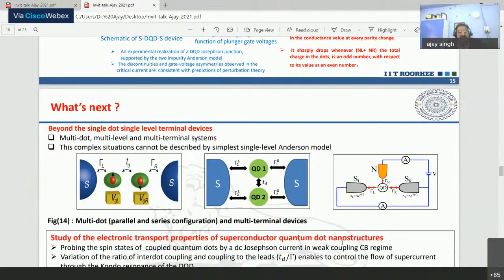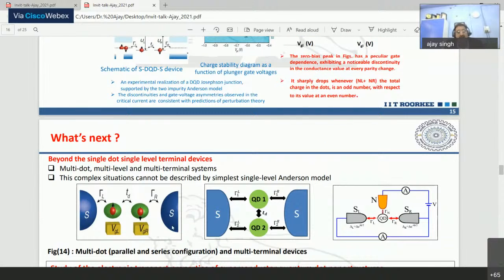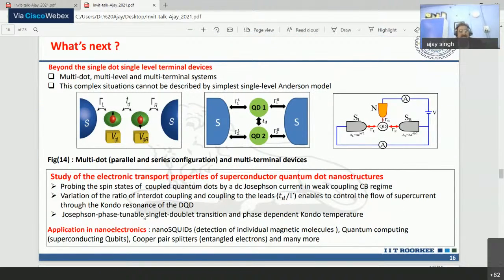So we have recently focused on these double quantum dots embedded in a superconducting state. We were granted a core DST project, and in this work I collaborated with Professor Vidyadhi Raja from JNCASR, one of the pioneers in NRG from the group of HR Krishnamurthy. So these results actually compel us to think about the superconducting state, when you see its effect on the magnetic moment on the impurity, and the impurity level is close to the Fermi level, so there is a tunability of the Josephson phase and singlet doublet transition phase, and there is a temperature which has to be scaled with the Kondo temperature, which is actually lower than the Kondo temperature.